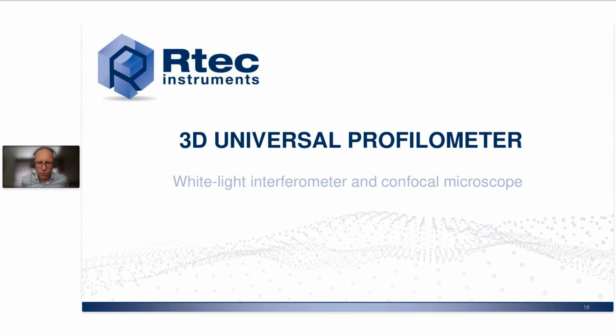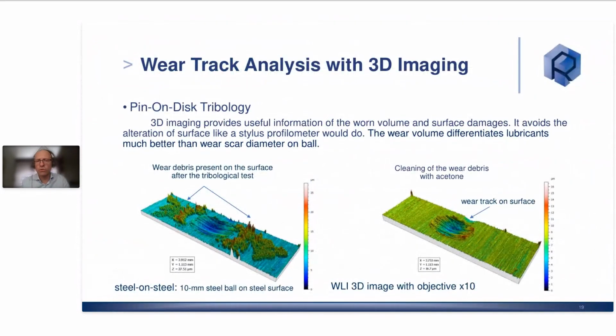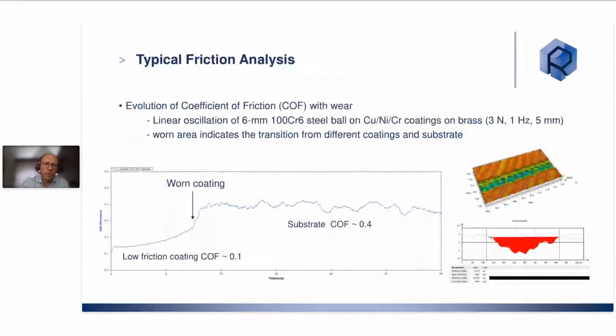So to just conclude on this kind of measurements, I explained shortly that we have a 3D profilometer combined to the tribology measurements, and that makes it very useful for characterization of wear on the material. You can imagine stopping the tribological test at different cycles or different levels in order to make a 3D image of the surface, and then bringing a little bit more insight or more advanced vision about how much is the level of plastic deformation and wear on the material while you are doing tribological testing.